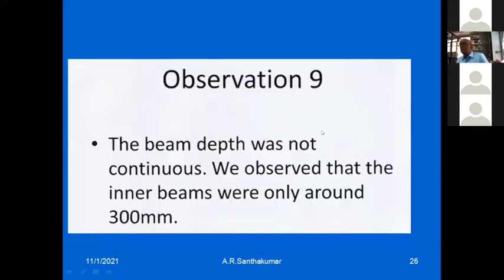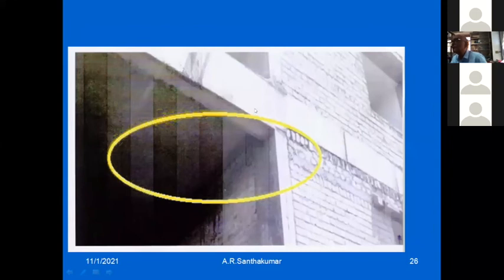The beam depth was not continuous. We observed that the inner beams were only around 300 mm. You can see the beam depth here and the beam depth here do not match. Here the beam is deeper, here the beam is shallower, and the level of the beam is also not uniform.